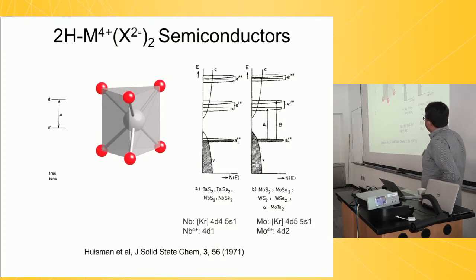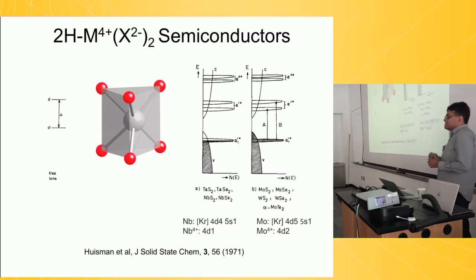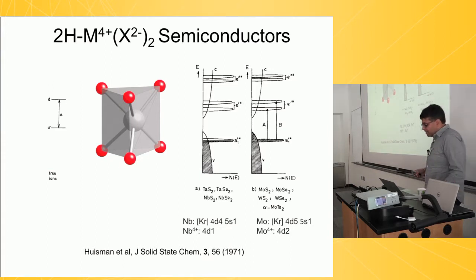So for example, if you put niobium, which when all said and done, niobium 4 plus is in a 4d1 configuration, that means I have one electron in this lowermost d orbital. And so it's a half-filled d orbital, and you expect this to be a metal. Whereas if you look at the ones that I'm going to talk about today, MoS2, MoSe2, and so on and so forth, the molybdenum in this particular case is in a 4d2 configuration, and 4d2 is going to fill this lowermost d orbital. And so just from this very simple picture, you expect this thing to be a semiconductor. And this is somewhat important when it comes to magnetism. I'll come back to this picture in a second.